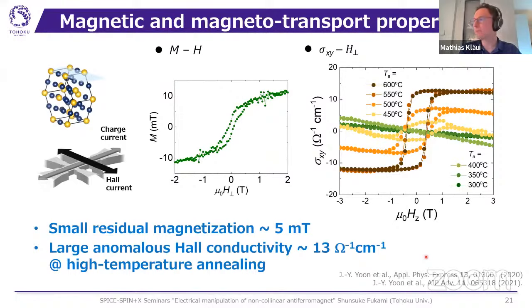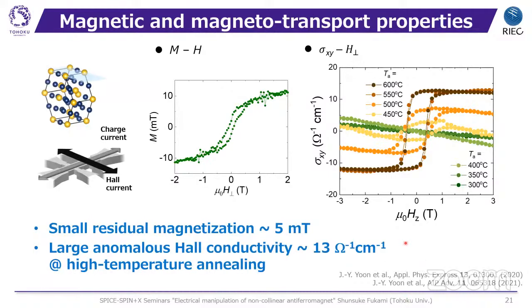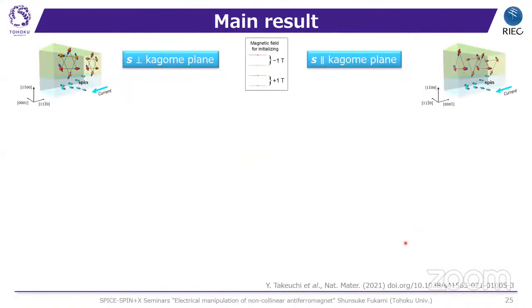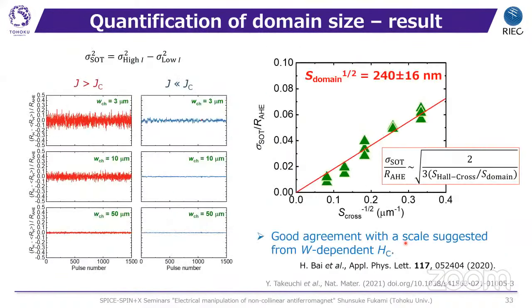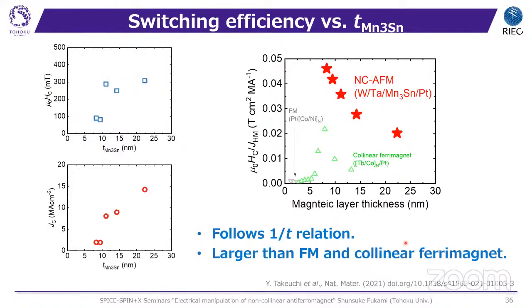So Dongwook, please go ahead. Thank you very much for an interesting talk. My name is Dongwook Go. Can you hear me? Yes. I have a question regarding the spin absorption in the non-collinear antiferromagnet as compared to spin absorption in a ferromagnet. In the ferromagnet, I think there is a good consensus about how the spin is absorbed, basically by spin precession and cancellation of electrons with different wave vectors, which leads to spin dephasing. You mentioned that the physics is different in non-collinear antiferromagnets. So how is the physical picture different from the ferromagnetic case when the spin current is absorbed into an antiferromagnet? The key question is, we inject angular momentum into the system, but where does the angular momentum go at the end? Because in an antiferromagnet, there are no net magnetic moments. So to me, it seems a little bit confusing. Could you clarify my concern?